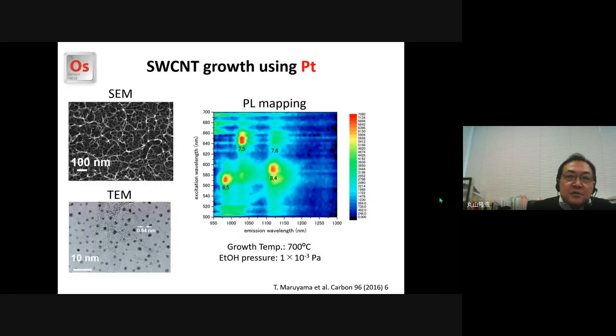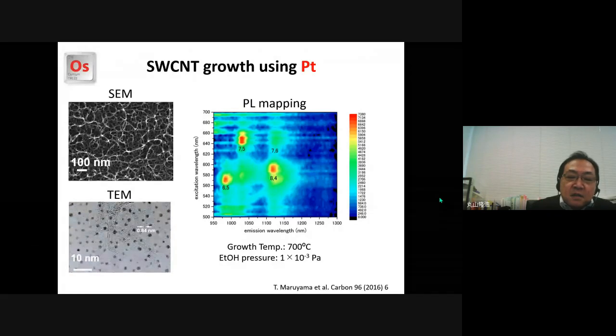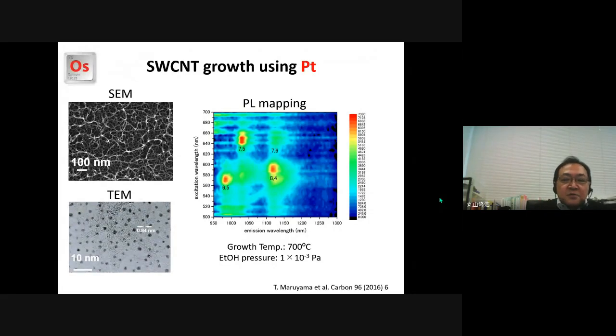The left figures show SEM and TEM images of the sample grown at 700 degrees C. This sample was the carbon nanotubes grown from platinum catalyst. So wave-like structures were seen on the substrate, and single-wall carbon nanotubes were observed in TEM image. The right figure shows PL, photoluminescence mapping of grown SWCNTs. PL mapping can determine chirality of semiconducting carbon nanotubes. Next slide, please.